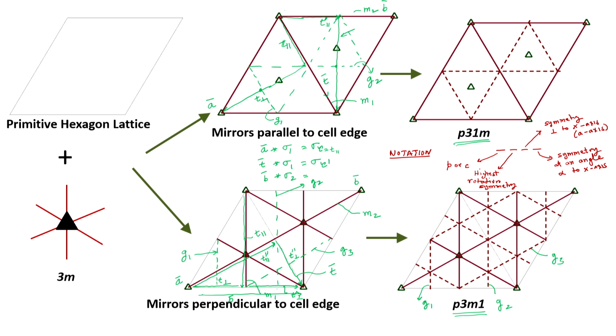Well, in this case, we do not have any. In fact, the second and third symbol will always be either a glide plane or a mirror plane. So, there is no glide plane, no mirror plane perpendicular to in fact any of the axes. Which basically means it is a one fold symmetry or no symmetry. So, the third symbol becomes 1.